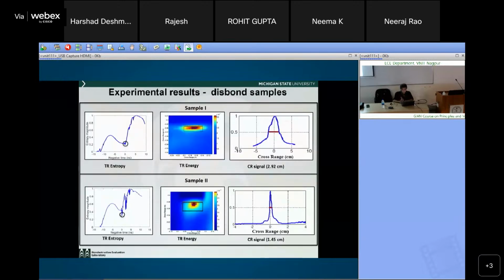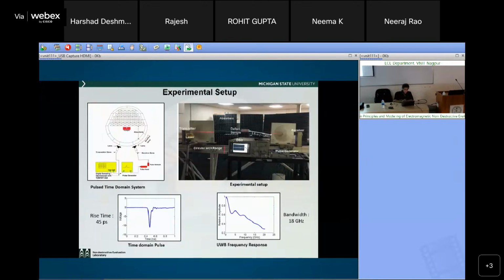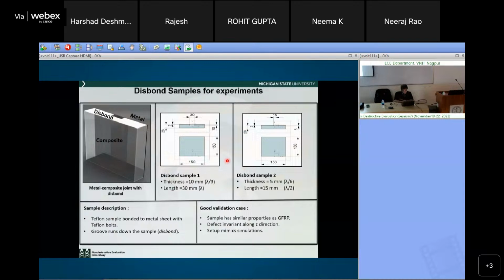And we did exactly the time reversal part. This was the setup. The sample is kept over here, and we had the source and an array of receivers. Time reverse the receiver signal, propagate the perturbation field using the model, look at the integrated energy, and you find the disbond. It comes back to focus at the disbond. And this is the entropy versus time. This is the minima of the entropy, and at that minima, when you plot the fields, you once again see a much stronger focus of the fields at that point.